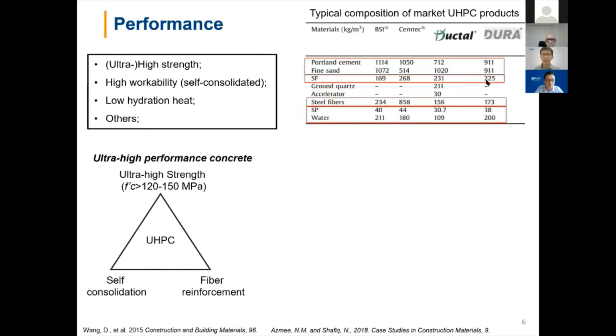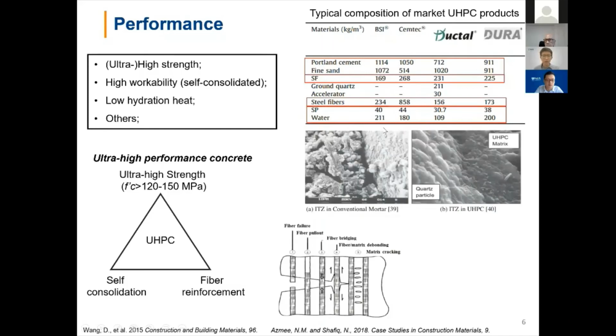There are already some market available products. If you look at the recipe of these products, you'll see that they all have a very high content of Portland cement, at the scale of already 1,000 kilograms per cubic meter of concrete. They all use fine sands instead of the combination of fine and coarse sands. They all have a high dosage of silica fume, of steel fibers, of water reducer, and a very low usage of water.